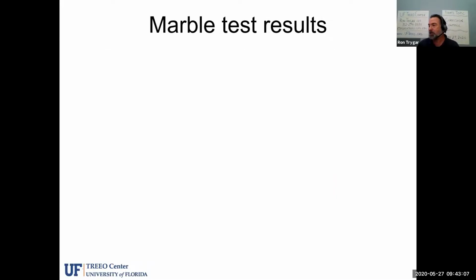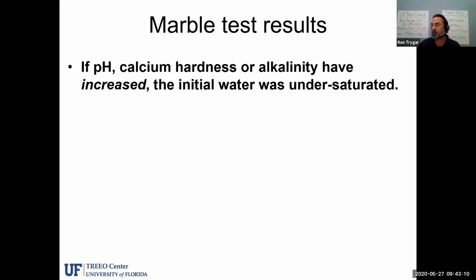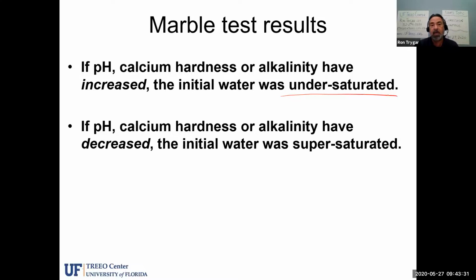So let's take a look at some other results here. You'll notice that it says if the pH, the calcium hardness, or alkalinity have increased from the initial sample, after we remeasured following the dosage of the lime or the calcium carbonate, then the initial water was undersaturated, which means that it was corrosive. If the pH, the calcium hardness, or the alkalinity, or all three have decreased, especially the hardness and the alkalinity, then the initial water was already saturated or supersaturated, and it allowed this stuff to come out of solution. So it was already at the saturation point, and that water would be scale forming.